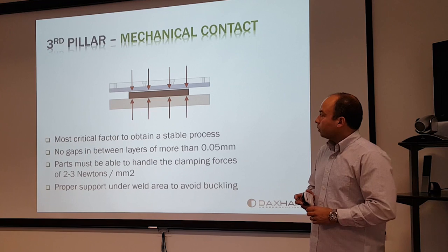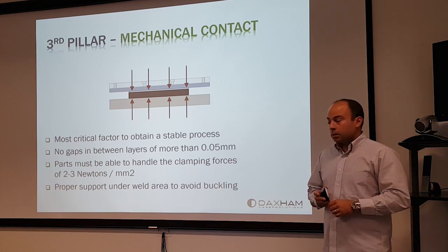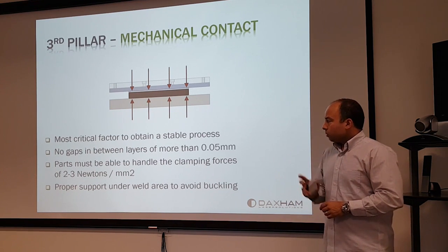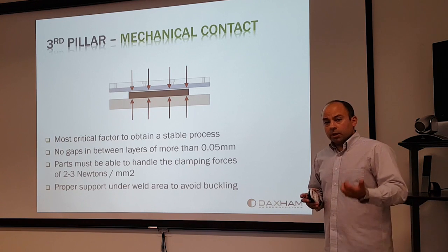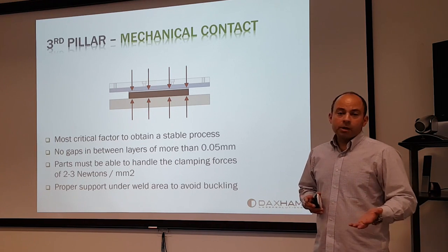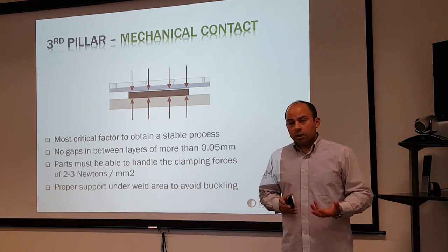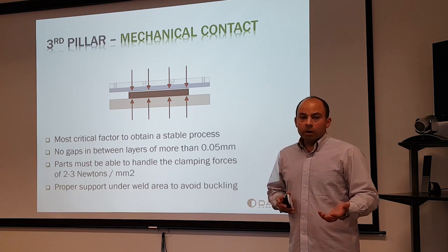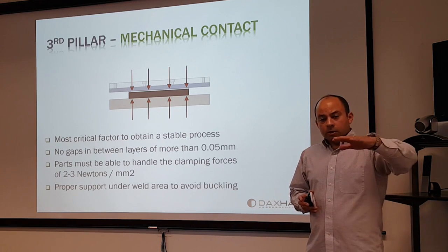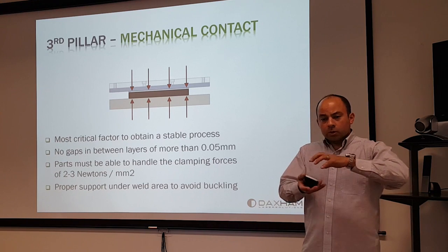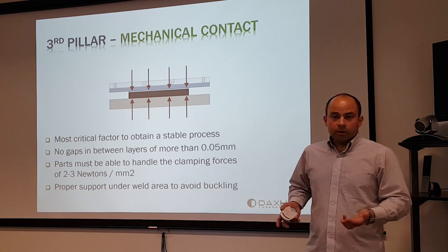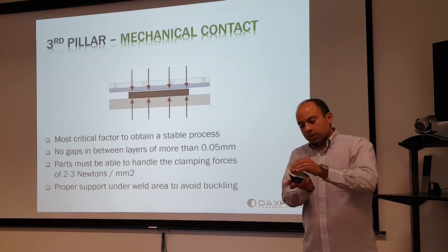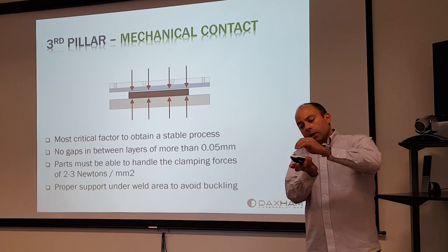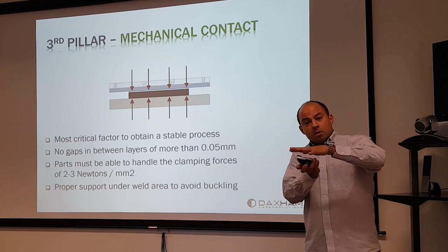The third pillar is mechanical contact. This is the most critical factor in order to obtain a stable laser welding process. I've seen so many times in the industry where clamping is subpar, substandard, and it allows for warps or twists or gaps, and your part is not going to weld. Bottom line, if there's a gap between the upper layer and the lower layer, you're not going to get any heat transfer because there's no mechanical contact.